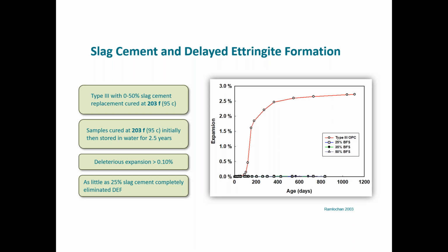And it creates a lot of heat of hydration very early. We grind it fine and select chemistry to solicit very early reaction, because in some environments like precast concrete and others, post-tension construction, time is very critical. So you look at these mortar bar samples that were created. They essentially made these samples and cured them at 203 degrees, and remember we said earlier 158 degrees is considered the critical point for an OPC mix, and 185 degrees is for a mix with SCMs.